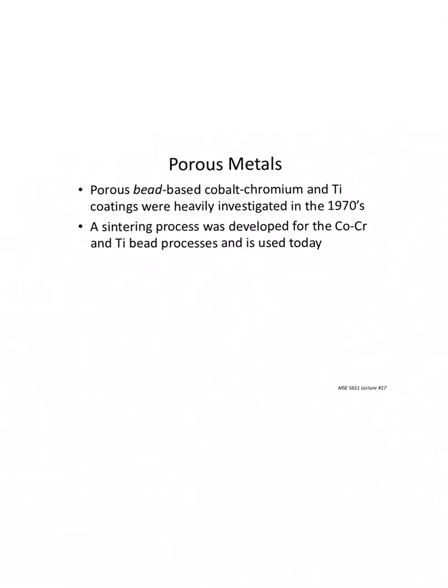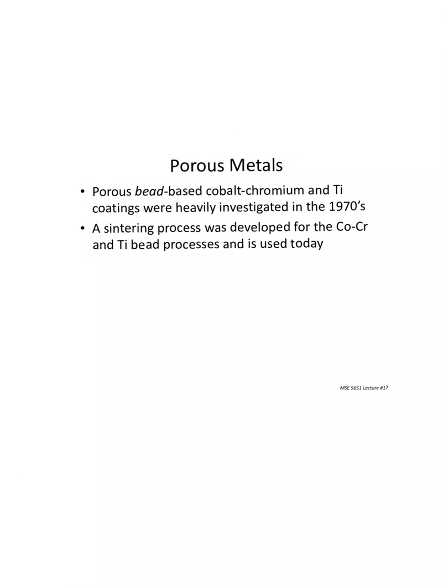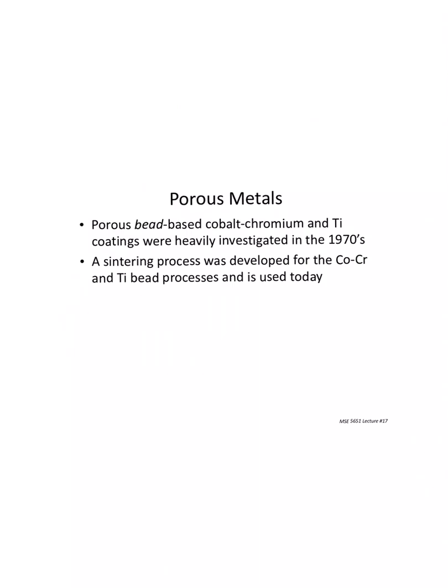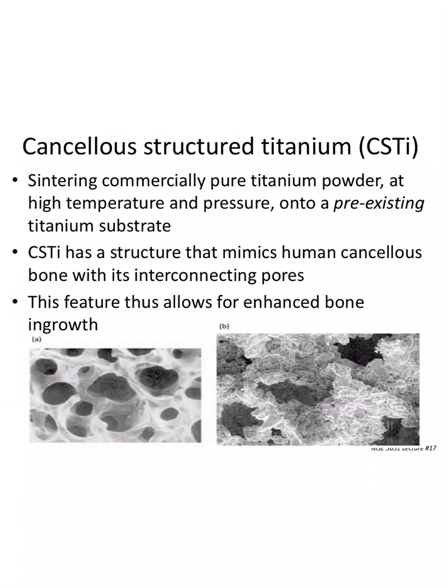And so, these porous bead-based coatings, I just gave you this cartoon already, were heavily investigated starting in the 1970s, and it was developed for cobalt chrome and titanium bead processes, and is still used today. All right, exactly what I said before, beads sitting on surfaces, you form a sinter neck, and boom, you've got a product. So everything we learned about sintering and transport and so forth applies to the development of these bead coatings on the surface.